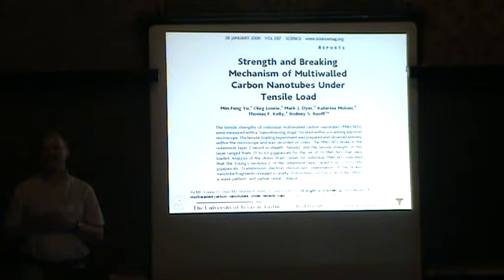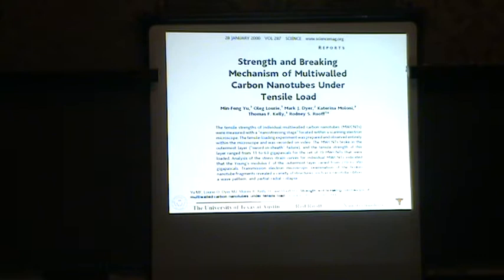So without us actually realizing it, which experimentalists should know, and sometimes we didn't, Andy had actually done a particular type of oxidative cleanup that they had developed in the Smalley group but not really advertised that broadly. And that involved exposure to carbon dioxide at elevated temperatures such as around 700 degrees Celsius. And about 90% of the carbon was thus oxidized away. And the remainder would be quite clean if you're looking with a scanning electron microscope or perhaps with TEM. The polyhedral particles and the amorphous carbon were more reactive and they were digested and removed through that oxidative treatment.